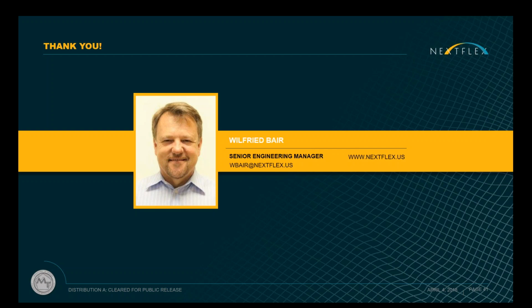All right. Thanks for leaving so much time, because now let's move on to the technical questions. Okay. Did you have any specific reason for using conductive adhesives and not solder for the SMT component attach? Yes, there are actually several reasons. The first one is when you use PET polyester, the processing temperature that the substrate allows is much, much lower than you need for solder. The second is when you do flex testing, solder is not the best material for flexing the interconnect. The adhesives have much better properties to do so.